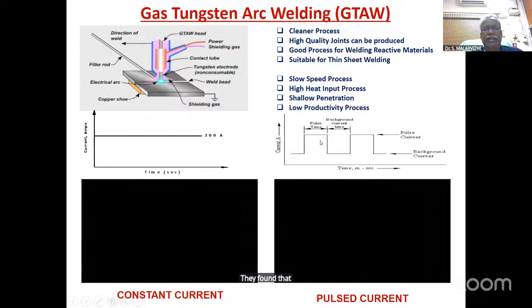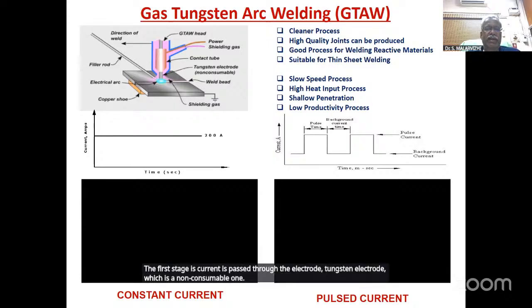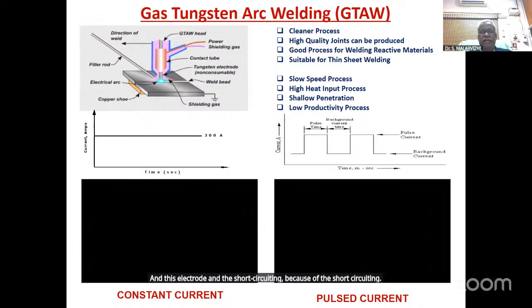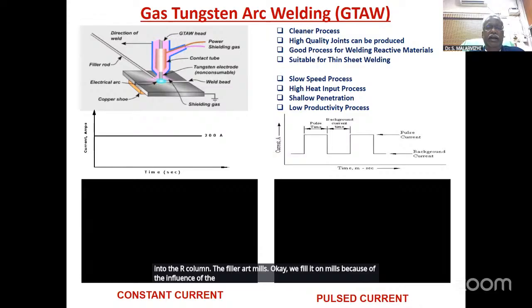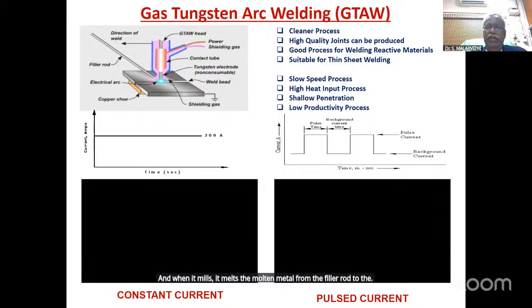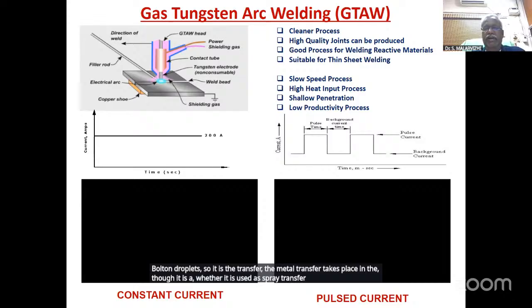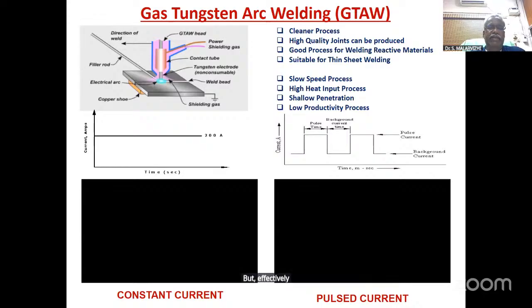They found that the welding involves different stages. The first stage is that current is passed through the tungsten electrode, which is the non-consumable one. Because of the short circuiting, the arc is established. Once the arc is established, you introduce the filler rod into the arc column. The filler rod melts because of the influence of the arc, and the molten metal from the filler rod goes to the weld pool in the form of molten droplets. So it is a metal transfer. Whether it is spray transfer, globular transfer or dip transfer, whatever the mode, effectively the metal transfer from the tip of the rod to the weld pool is drop by drop.